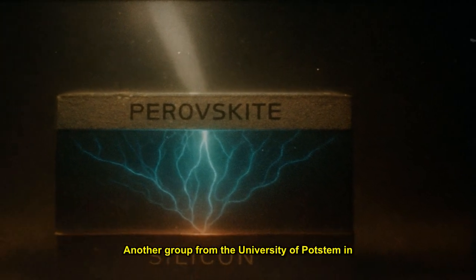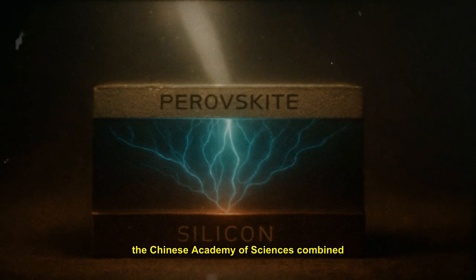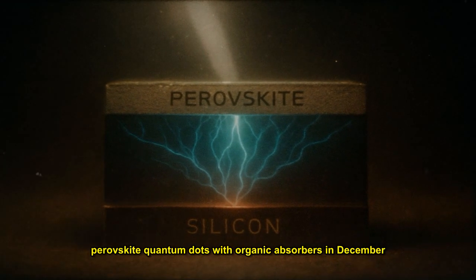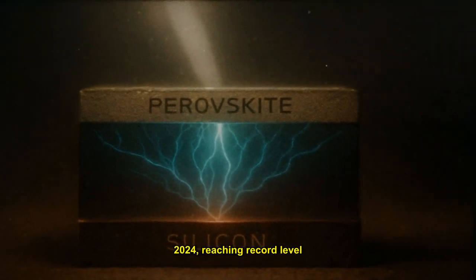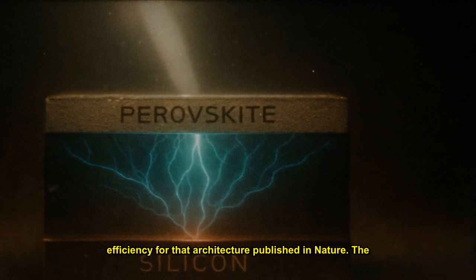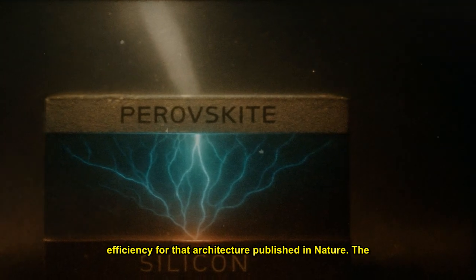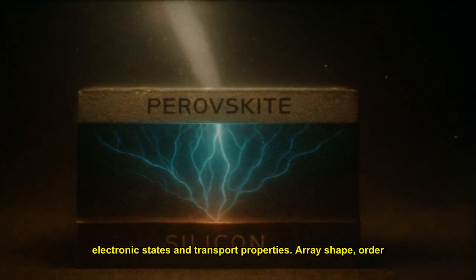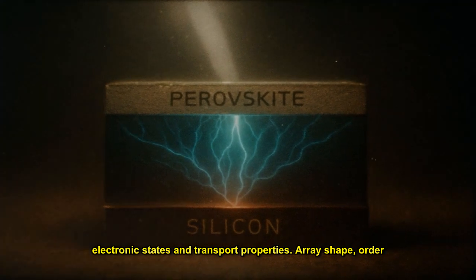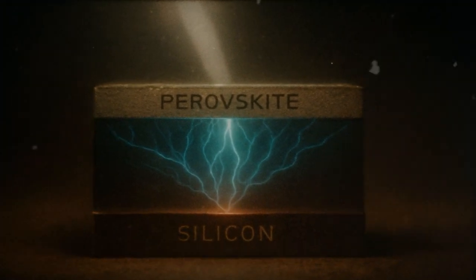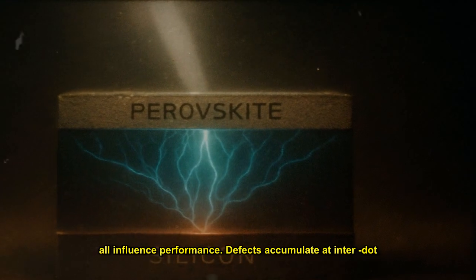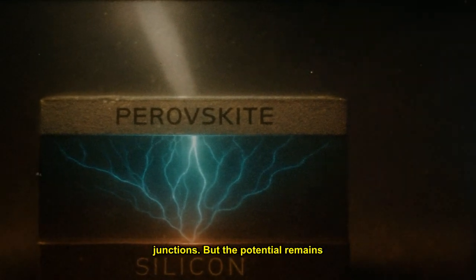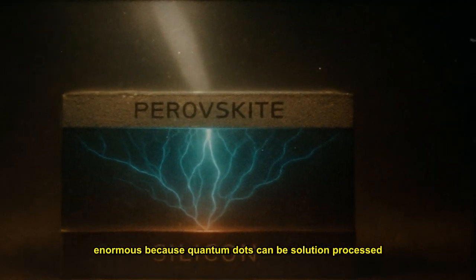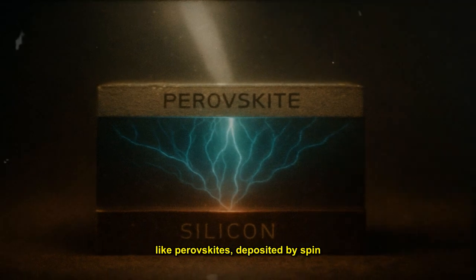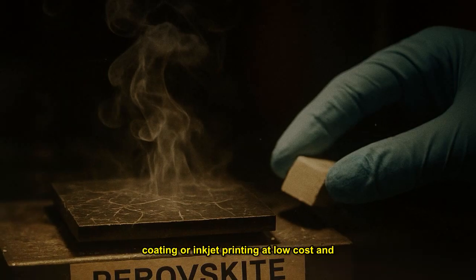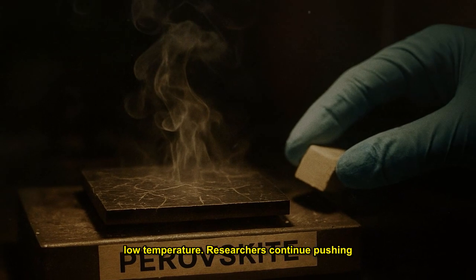Another group from the University of Potsdam and the Chinese Academy of Sciences combined perovskite quantum dots with organic absorbers in December 2024, reaching record-level efficiency for that architecture, published in Nature. The spacing between dots affects electronic states and transport properties. Array shape, order, disorder, and dot orientation all influence performance. Defects accumulate at interdot junctions. But the potential remains enormous because quantum dots can be solution processed like perovskites, deposited by spin coating or inkjet printing at low cost and low temperature.